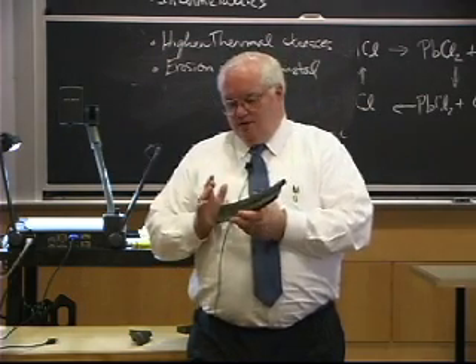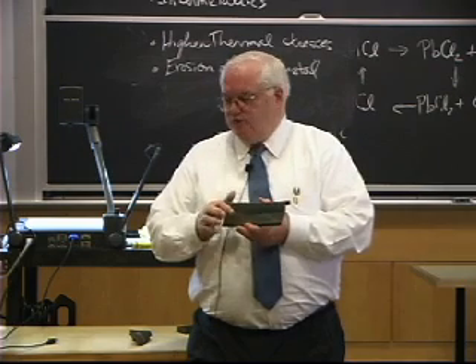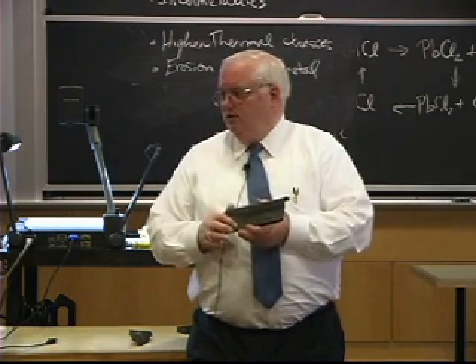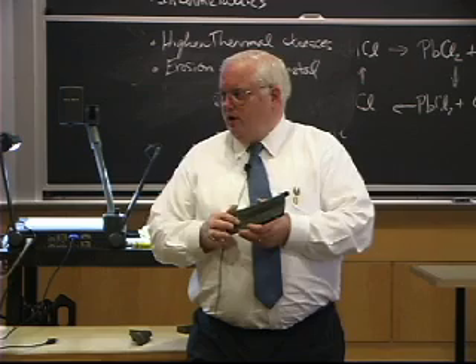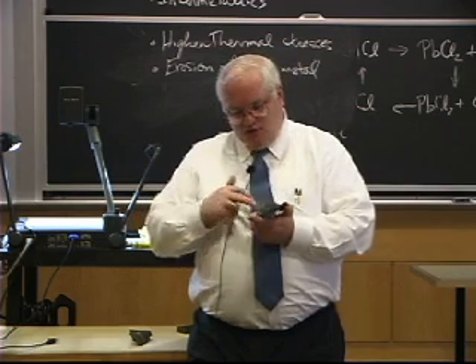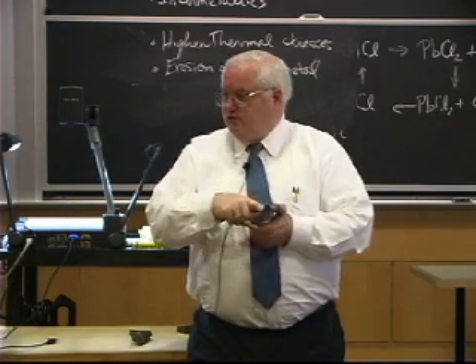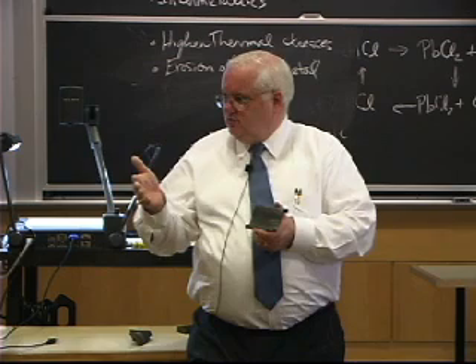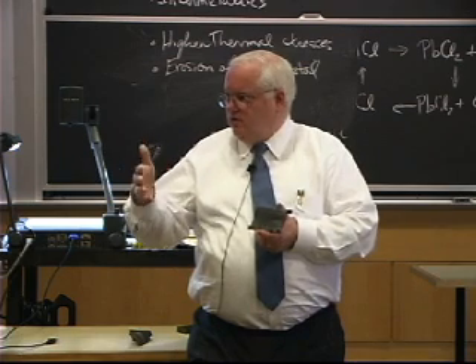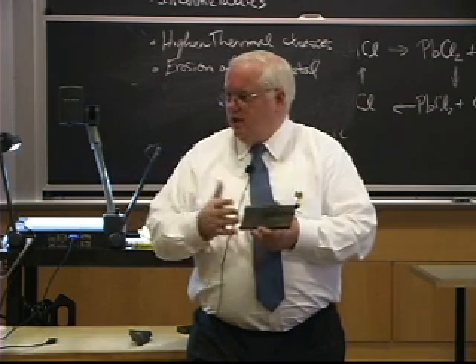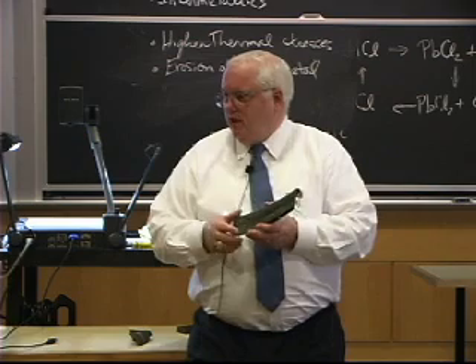So that is an application where you have some very thin material, and if you have very much erosion in your braze, when you make the braze joint, and this thing starts out at 5 thousandths thick material, if I got 2 thousandths erosion on each side as the braze alloy dissolves some of the base material, I'd have a problem. I wouldn't have much left.